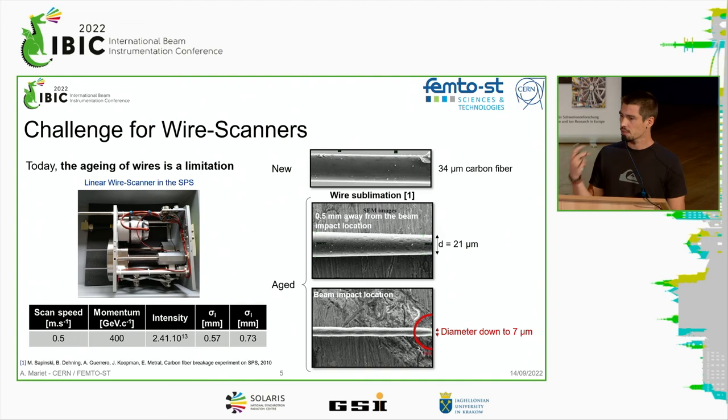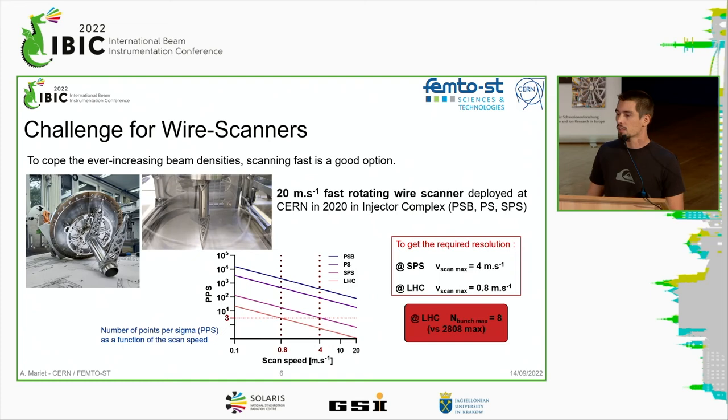So we already observed in the SPS, in certain conditions with slow linear wire scanners, a degradation of the wires, with a sublimation of 80% of the diameter, remaining only 7 microns of material in the middle. So this is an issue. To solve this issue, we developed a new generation of fast wire scanners, which is